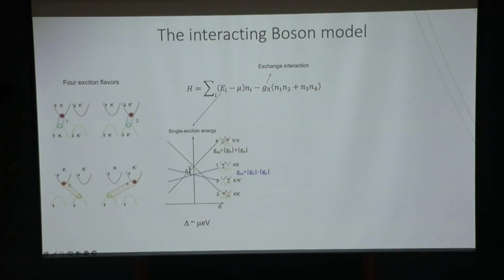So let's see what the single-particle energy looks like and how the interaction modifies the behavior. Again, there are four different exciton species. When you look more carefully, the intravalley excitons are linked by time reversal symmetry, so they must be degenerate. And these must also be degenerate by symmetry. But between these two, they're not symmetry protected, so it's possible to have a small energy difference between these two types of excitons. Let's assume there's a finite energy separation delta within the microelectron volt level.